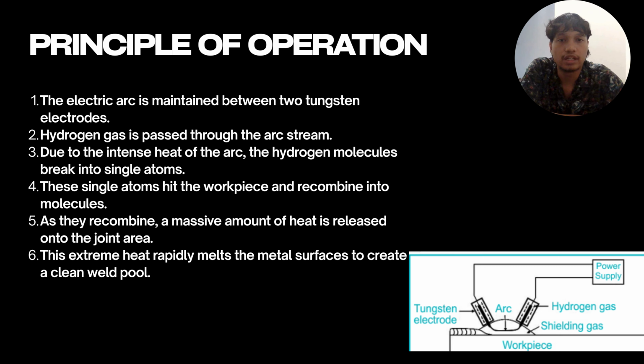Third, due to the extreme heat of the arc, which can reach up to 40,000 degrees Celsius, the molecular hydrogen gas absorbs a massive amount of energy and breaks apart, or dissociates, into single hydrogen atoms. This is a highly endothermic reaction. Fourth, these highly unstable single atoms are pushed out of the torch and hit the relatively cooler workpiece surface.